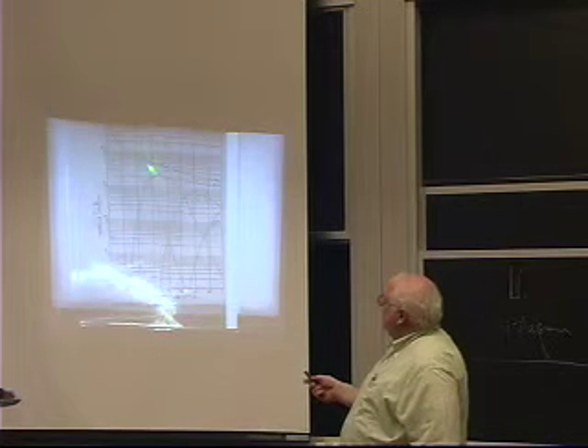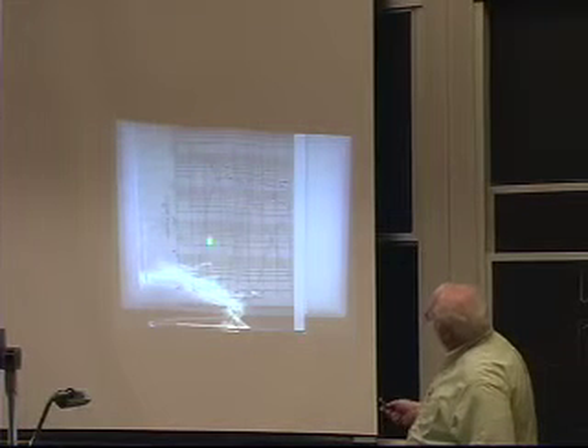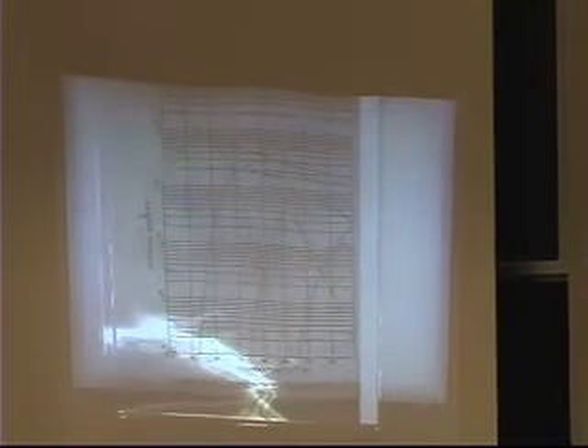Well, if you have pure argon at low temperatures below 5,000 Kelvin, essentially argon, this A line, which is neutral argon atoms, is equal to the total number of particles. That's all you got in your gas, is pure argon. However, as you get to around 11,000 Kelvin, according to this calculation, some of the argon will be hot enough, you'll start to strip off some electrons, and you now have the argon ion line, this is A+, and in fact that is exactly the same thing as N sub E, the number of electrons, because every argon ion you get one electron initially when you're singly ionized. So this thing is coming up, this is orders of magnitude here, okay? 10 to the 14th per cubic centimeter up to 10 to the 17th. And so the thing's starting to ionize.